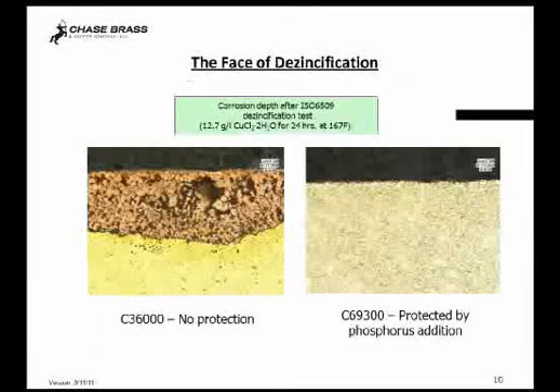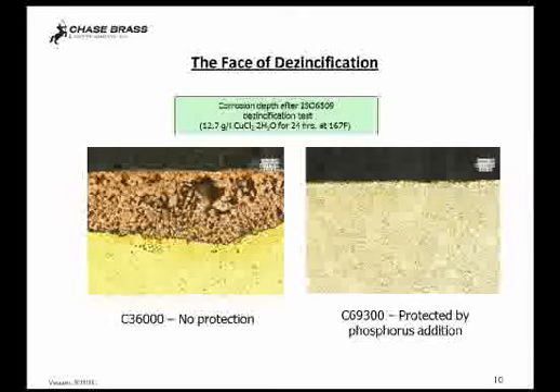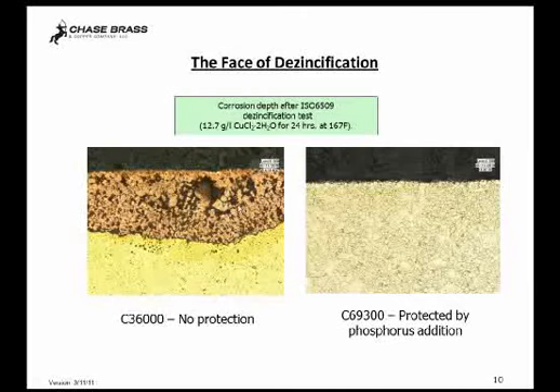Dezincification resistance is a little bit easier to show. And when you have no inherent protection of the material through its chemistry, what you can see under certain conditions is that the zinc will selectively leach from the brass and leave behind a spongy copper layer. NSF 14, as we said, allows no more than a 200 micron or 0.008 of an inch depth of corrosion in this standardized test, ISO 6509, before a part is considered to have failed.